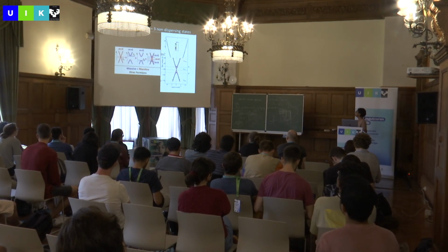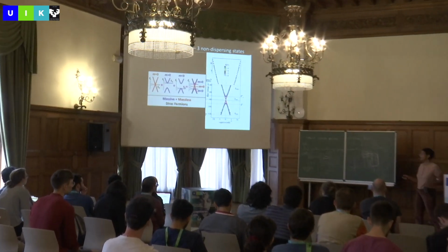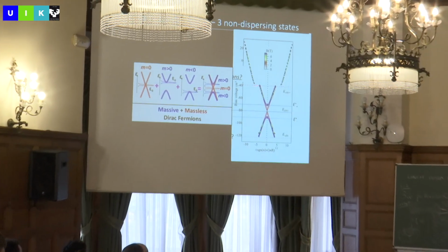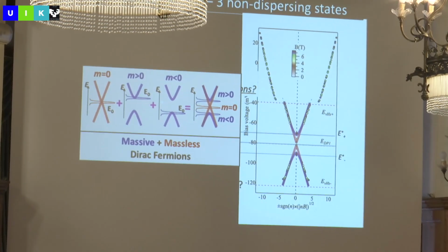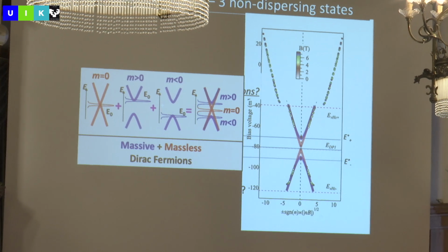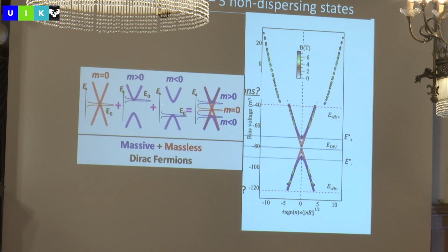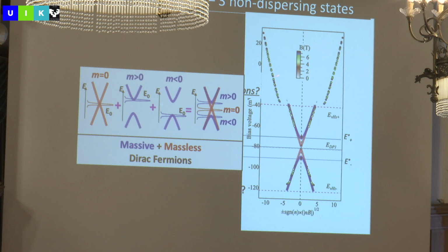Yeah. Oh, this is the Lifshitz transition. At the Lifshitz transition, where the bands on either side merge together, you should have a jump in the area. This is expected. And in fact, we can fit this really beautifully. The area should double at that point.